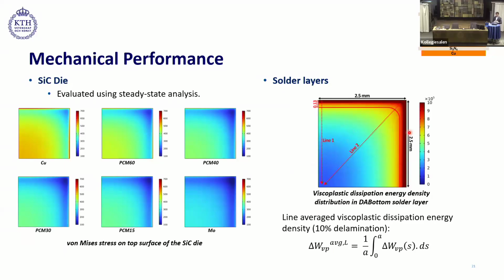So we have a quarter symmetric in this case. We use line 1 in this case to calculate the viscoplastic dissipation energy density. And based on 10% delamination criteria, we calculated this length, and we call it crack length, and it is 0.13 mm. And then this viscoplastic dissipation energy density in this crack was fed into this formula to calculate the line averaged viscoplastic dissipation energy density.